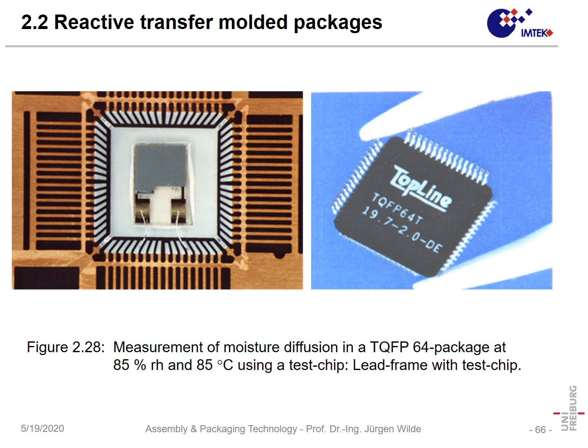What is your idea? Do you think it is a matter of minutes, of hours, of days? Of course, that's depending on the temperature. The higher the temperature, typically, the faster the diffusion. So we wanted to know this, and so we did a small experiment. We took a package that is a TQFP64 package. And in that package, we installed a capacitive moisture sensor.